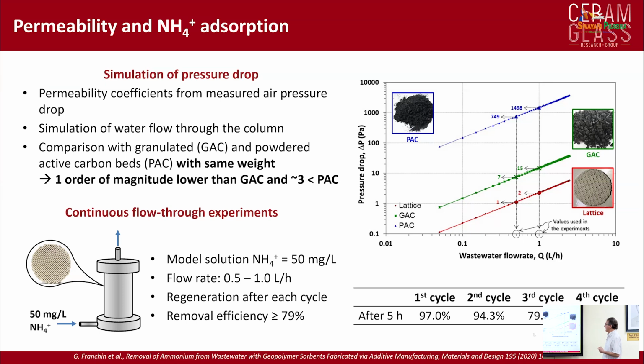Besides these data, what is interesting is that we tested our material versus other materials that have been proposed for the same application, and specifically active carbon and granulated active carbon. And these materials, of course, work well, but they are either in powder form or in granules. And if you look at the pressure drop provided by a powder bed or a bed containing granules, you can see that the powder bed has a very high pressure drop. The granules have a better performance, and that's why they make them. But it still has some significant pressure drop.